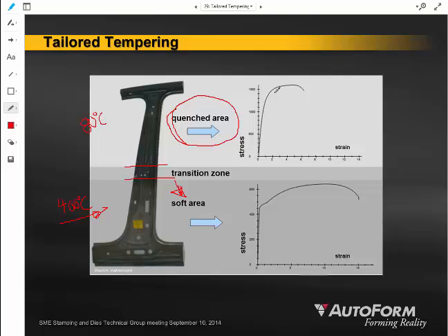And that means that we're going to have a much higher strength material at the end of the forming operation for this top part of the B-pillar, and then a much lower overall yield strength and tensile strength of the lower portion of the B-pillar. And that was engineered for and designed in order to give a certain product performance for that B-pillar that was selected by the structural or product engineer.